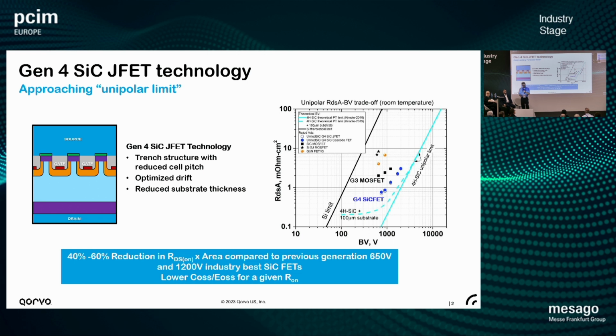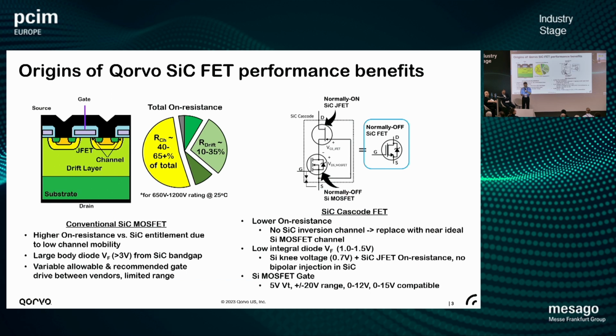We work on JFET technology because with JFETs, we don't run into gate oxide issues or channel resistance, which allows us to make the chips achieve lower resistances in a given size. So that's what you're seeing there. That's why the blue dots tend to be lower than where the MOSFETs fall or where a GaN device would fall in this RDS on versus breakdown plot. And this is just explaining the reason for why that happens, which is the nature of the oxide interface you get in silicon carbide. So what we build are normally on JFETs.